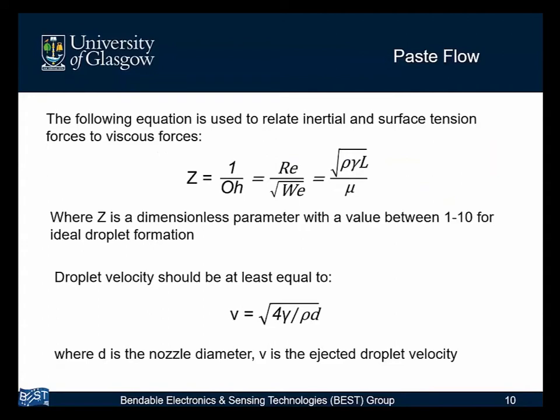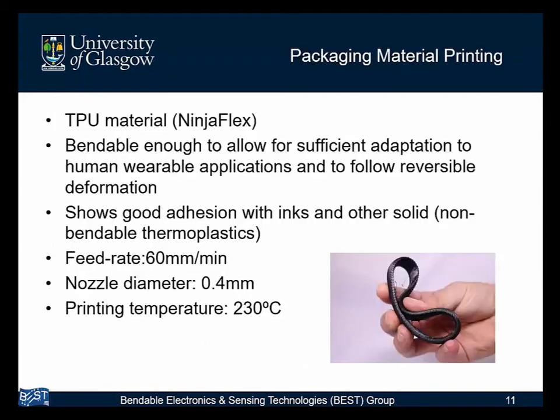In terms of paste flow, we can look at different properties. Specifically, with the specific properties of the paste itself, we can alter the velocity at which it's printed, and in turn, the feature size which we can get, and the repeatability of the prints. Particularly, we look at the density of the inks, the viscosity, surface tension, and the droplet diameter as well. Eventually, we're interested in the velocity of printing. We're interested in the parameters of printing instead of the feed rate of the extruder mechanism, to be able to get the most reliable and repeatable results in terms of this printing mechanism.